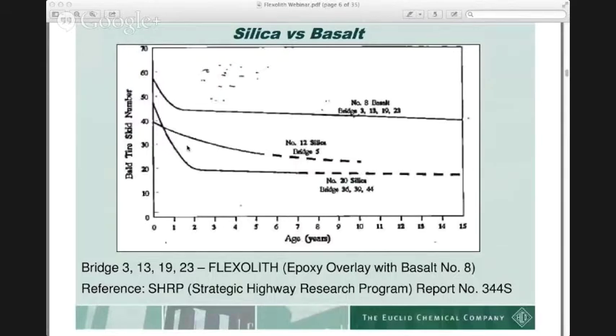which shows under the bald tire skid resistance numbers, very stable numbers at around 45 to 48 after the initial year, compared to the silica sands, which are typically down around the 20 mark. So the basalt seems to be a more aggressive aggregate, and it holds up a little bit better. Next slide.